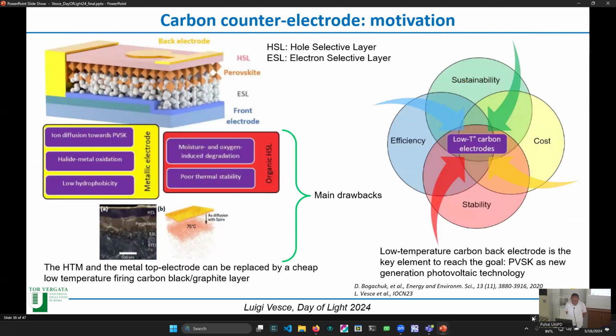There are some motivations in general to substitute the gold counterelectrode, as I anticipated, because with the metallic electrode you have some ion diffusion towards the perovskite, as we discussed this morning, and also you have some halide-metal oxidation. The gold has a very low hydrophobicity, so this means that you have more impact with respect to moisture, and also you can avoid using organic HTL that has very poor thermal stability. So in the last years, the scientific community believes that the carbon counterelectrode can in such a way meet all the needs for the technology.